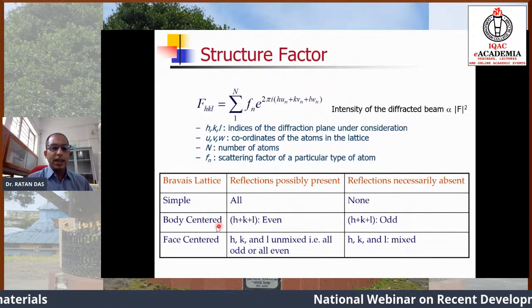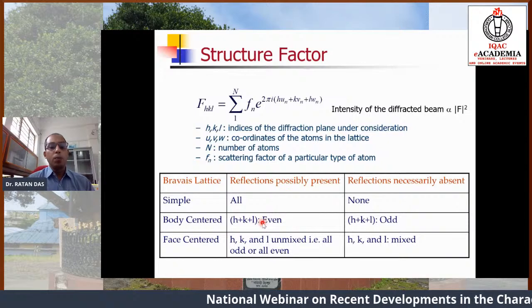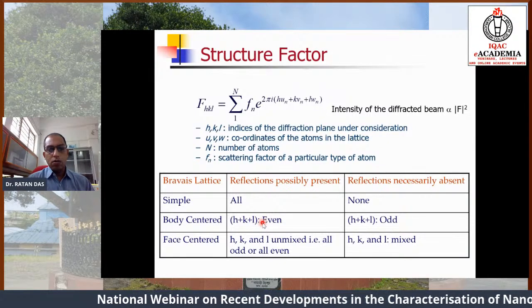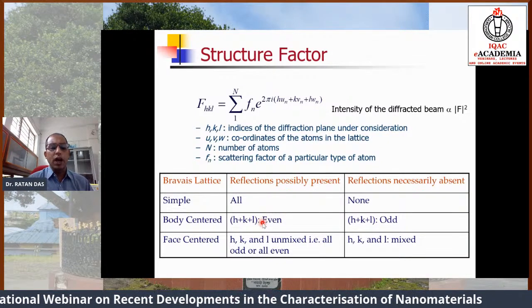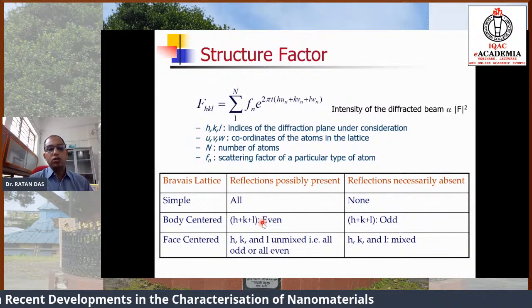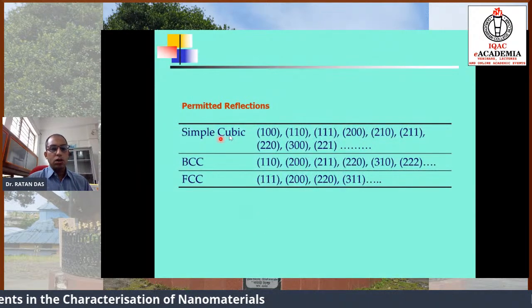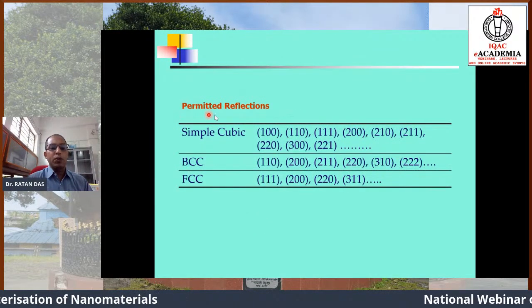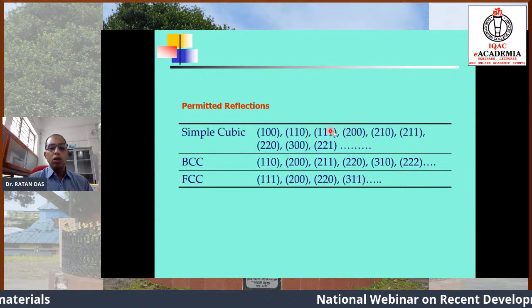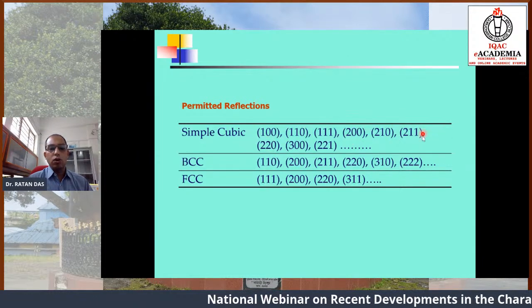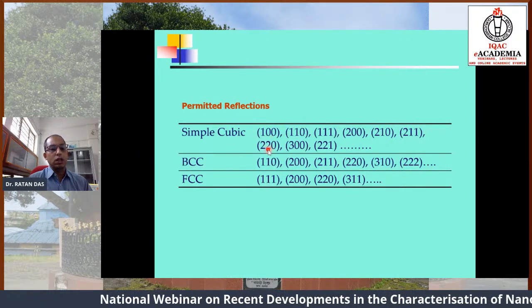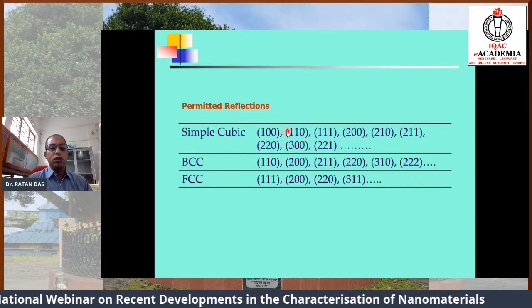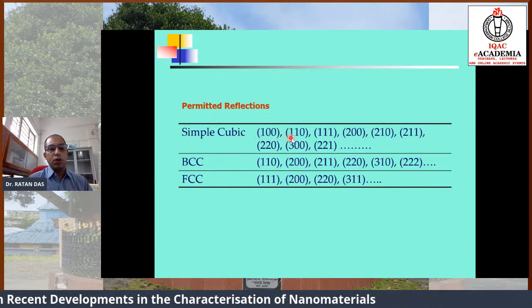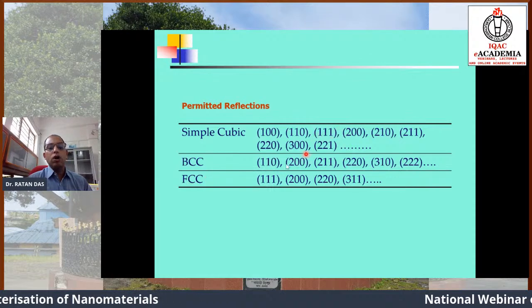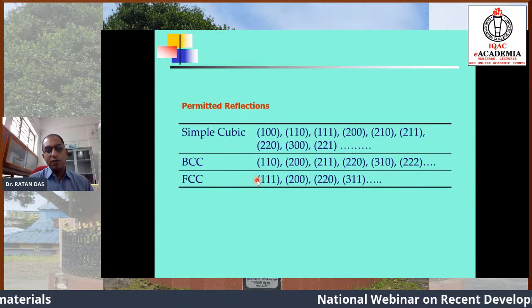So what are these HKL actually? HKL is nothing but our Miller indices. So you have to know these Miller indices beforehand before going to the X-ray diffraction analysis. Here are some examples of permitted reflections. Here you see all the Miller indices, all the reflection planes, are available. But in BCC you see 100 is not available, but 110 is available. In the case of FCC, 111 is available.